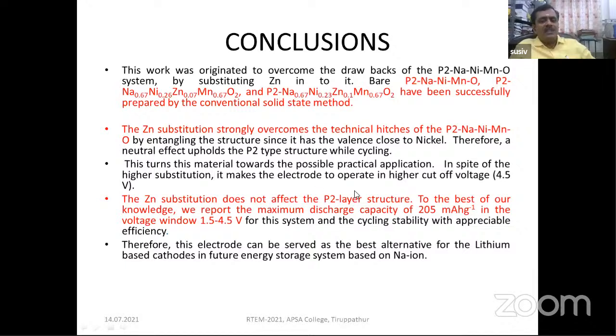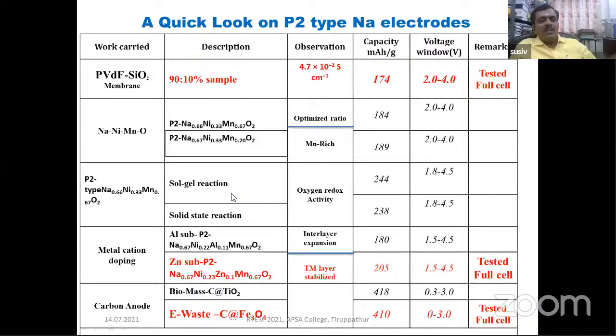But it doesn't affect the P2 type layer structure. And to the best of our knowledge, we report the maximum discharge capacity of 205 milliampere hour per gram in this voltage range 1.5 to 4.5. Okay, we can have a very quick look at the P2 type sodium electrode. We have prepared the PVDF SiO2 electrolyte membrane and employed it in this sodium electrode. We have attained 174 and tested in this range 2.0 to 4.0.